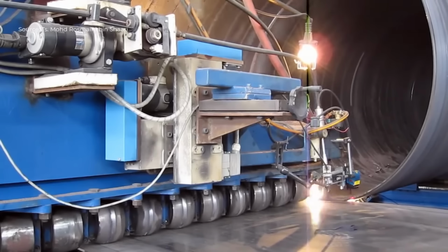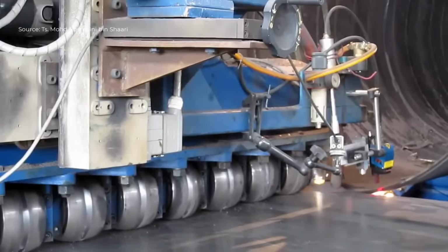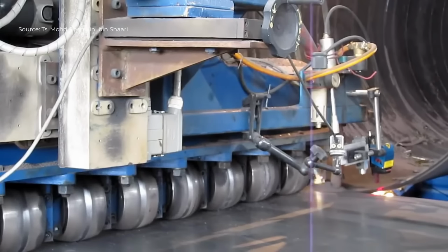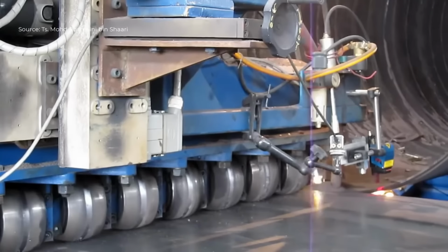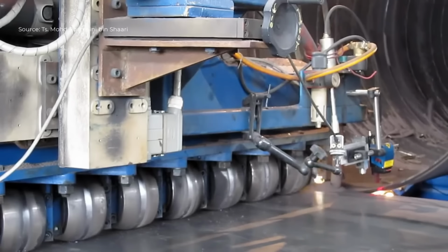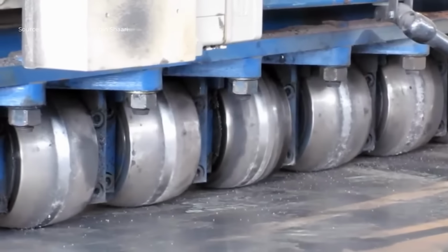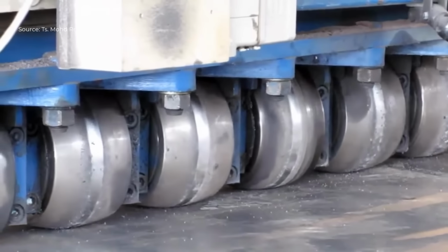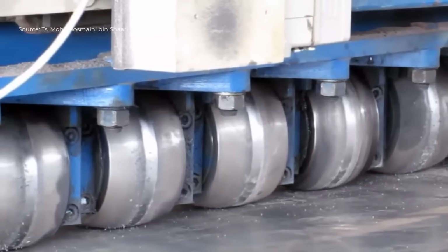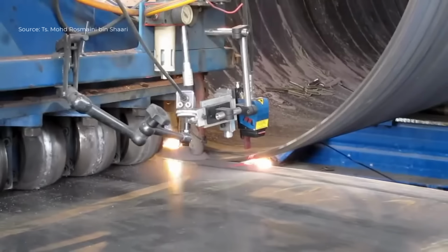The flux completely covers the arc, preventing atmospheric contamination, reducing spatter, and ensuring deep penetration. The welding machine moves steadily along the spiral seam, maintaining constant voltage, current, and travel speed to achieve consistent weld quality along the entire pipe length.